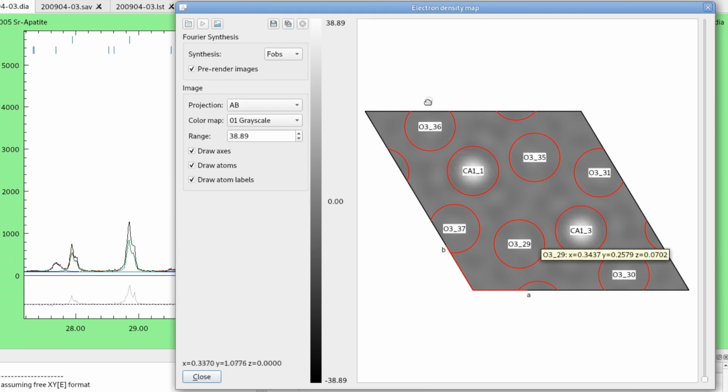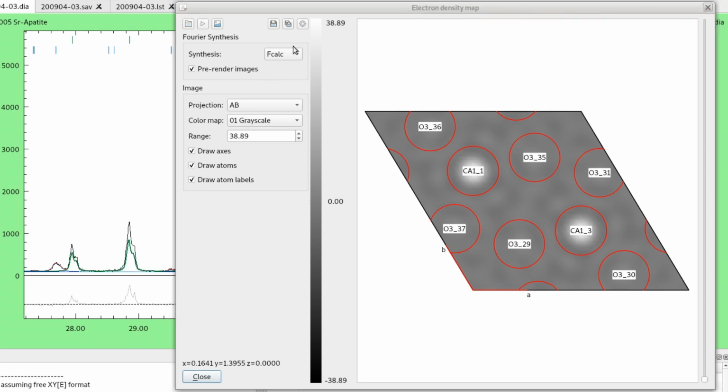these electron densities. We can change this to F calculated. So now we will be using the ones from the calculated diffraction pattern, this intensity. We don't have to reload the file, but we have to recalculate the electron density map with this data. So we have to click here, recalculate electron density map, because we changed this setting. And now we see the electron densities calculated from the calculated structure factors. We don't see much of a difference compared to the observed F structure factors, but we can choose the third